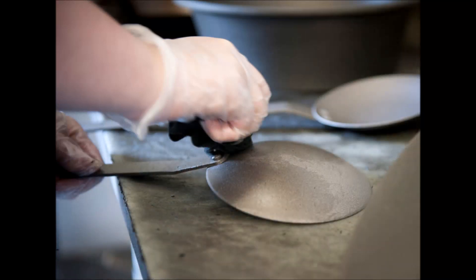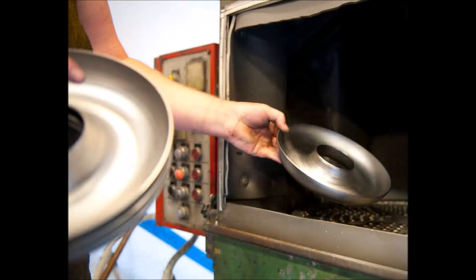We like to use flax oil — that's edible linseed. Clean a pan very, very well, making sure there's no oil on it. We actually ensure they're chemically clean — we don't use chemicals. We hit them with little bits of iron, very, very hard, so that there's absolutely nothing on the surface at all. We get rid of all of that, coat them in oil, and bake them very, very hot — about 300 degrees, hotter than you can really do at home. That's the start of a seasoning process.